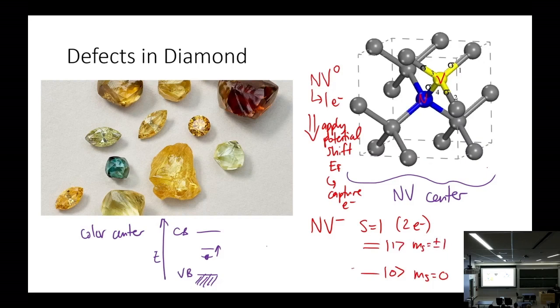And in diamond, this energy is in the microwaves. So I can probe or even pump transitions here using microwaves. But normally, just like in the vanadium example, I excite the system using light. I'm not using this little energy to excite the system.